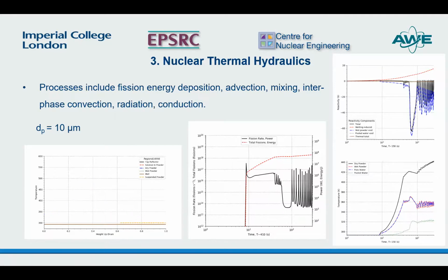So more energy is required to raise the wet powder and pool water temperatures. The conduction between the dry powder and wet powder isn't enough to decrease the amplitude of this sharp interface because the thermal conductivity of uranium dioxide is quite low. And that, coupled with the porosity that I've considered in my system, which is about 0.845, means the area for thermal conduction is also low, just adding to the sharp interface.